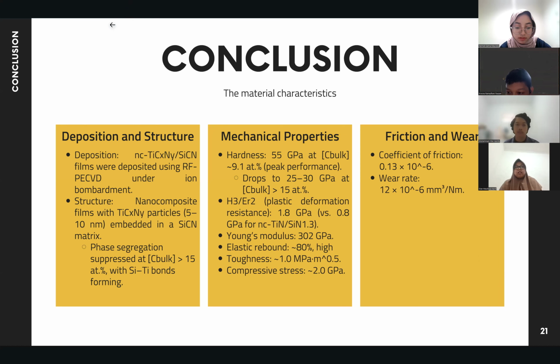The titanium carbonitride or silicon carbonitride films were deposited using PECVD under ion bombardment. As for the structure, the nanocomposite films are embedded in a silicon carbonitride matrix, which are 5 to 10 nanometers in size. It also consists of the phase segregation, which is suppressed at more than 15%, with silicon to titanium bonds forming.